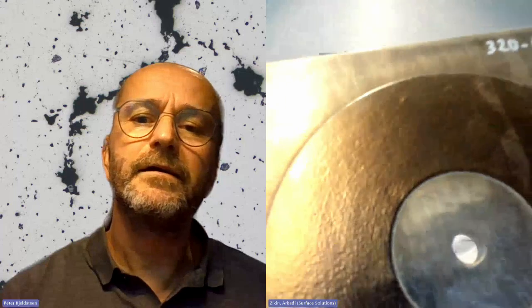Up and down behavior, because you do a line in the laser process and then overlap this line. In a high-speed process, your overlapping is around 90%. So you basically almost do not overlap. But due to the speed and velocity, you don't see this effect at all. But what we can do, you can also work with laser remelting, so you can even remove some roughness components from the surface. We have a bunch of experience in that. You get a really shiny surface out of that.